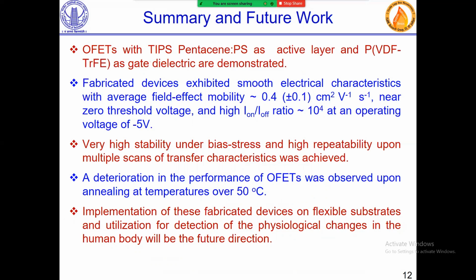OFETs with TIPS-Pentacene PS as active layer and PVDF-TrFE as a gate dielectric are demonstrated. The fabricated device exhibited smooth electrical characteristics with average field effect mobility of 0.4 centimeter square per volt per second, near zero threshold voltage and high on-off ratio of 10 to power 4 at an operating voltage of minus 5 volt. A very high stability under bias stress and high repeatability upon multiple scans of transfer characteristic up to 100 cycles were achieved. A deterioration in the performance of OFET was observed upon annealing at temperature over 50 degrees Celsius.